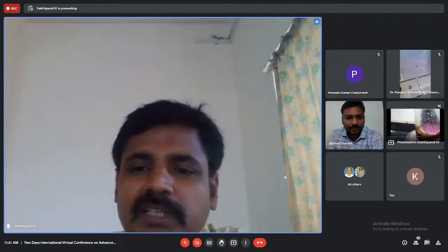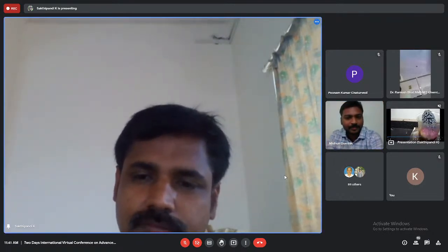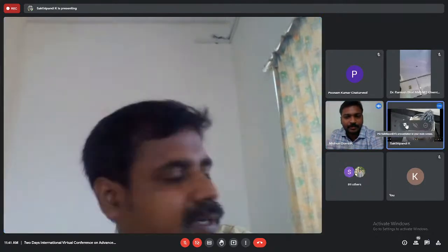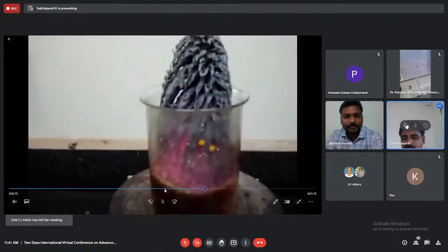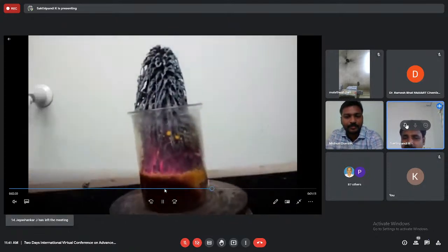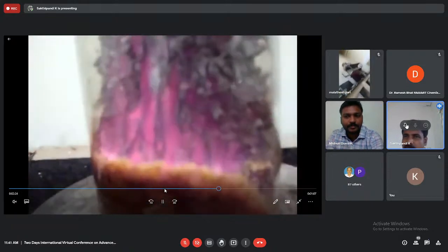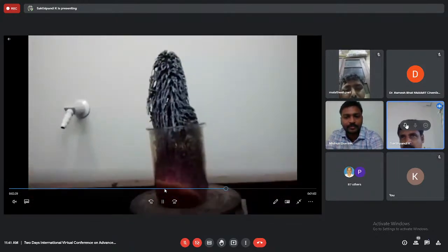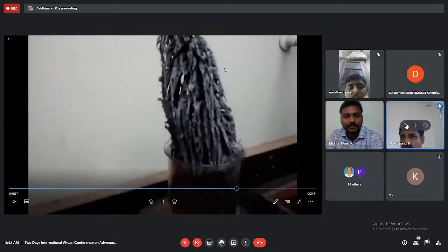This is another sol gel method. Generally the magnetic particles may be prepared by the sol gel method, but any method has some limitation based on the particle size. If you go for sonication, the particle size is around 40 to 60 nanometer. You can't get beyond this. For example, the ball mill technique is useful for bulk synthesis, but there also the particle size is limited. Around 60 nanometer only you can get from the ball mill.